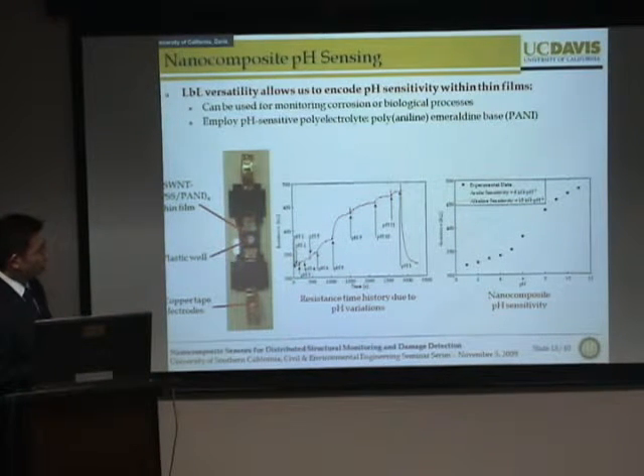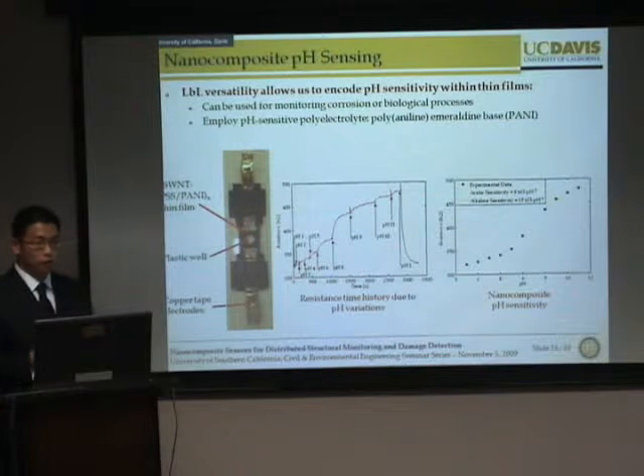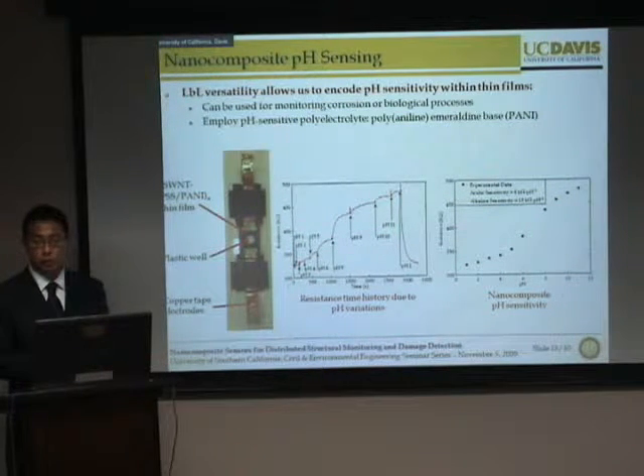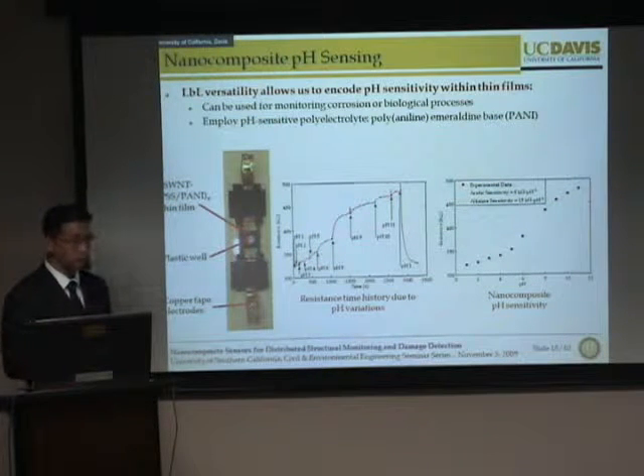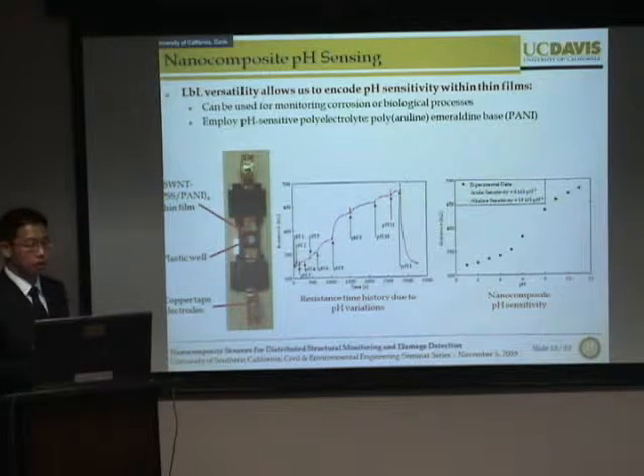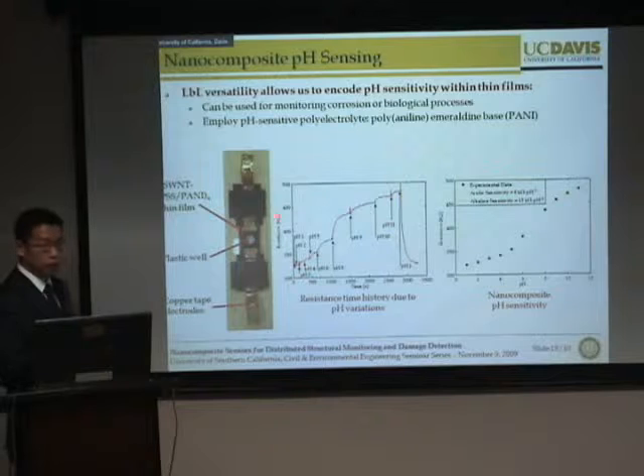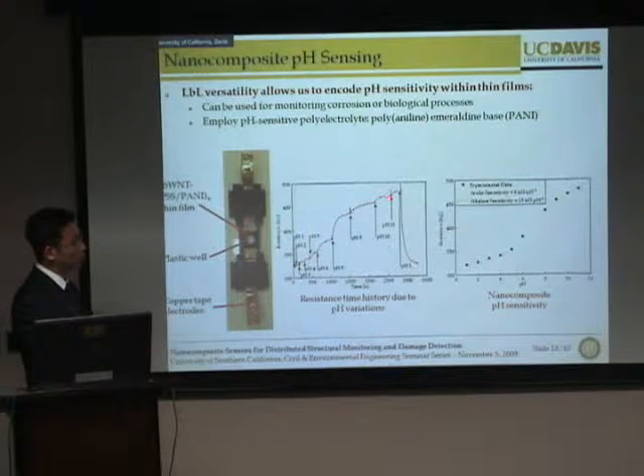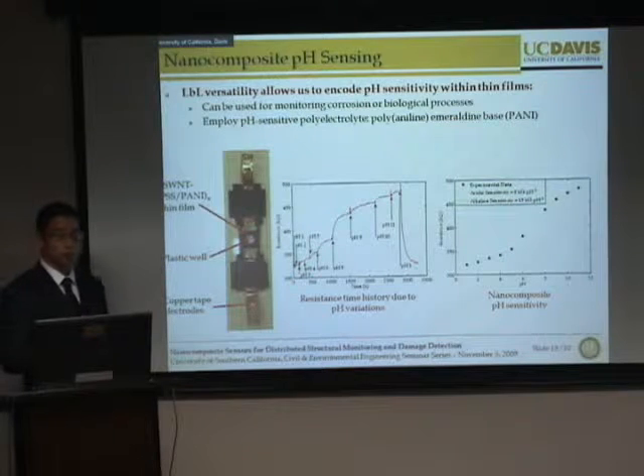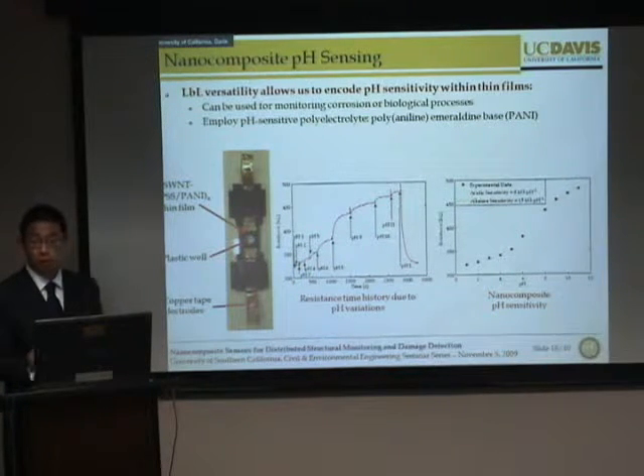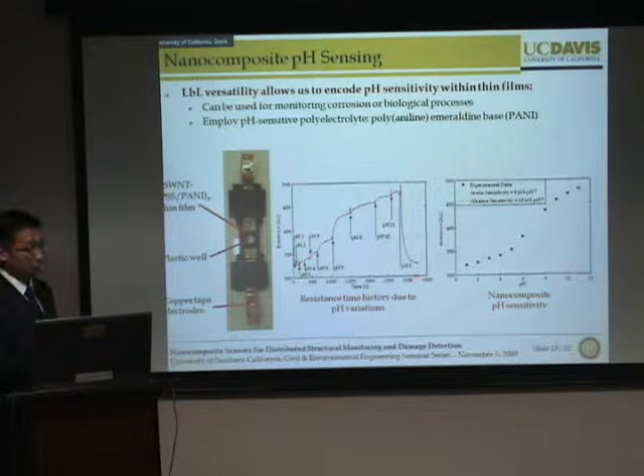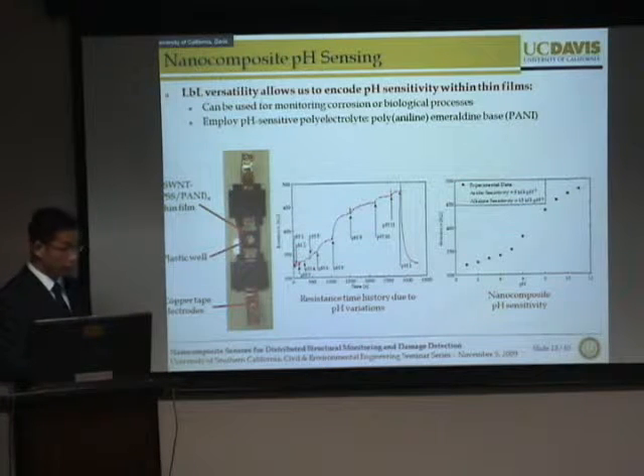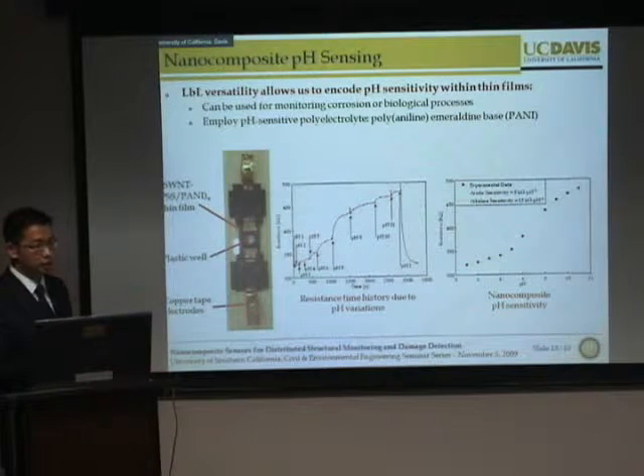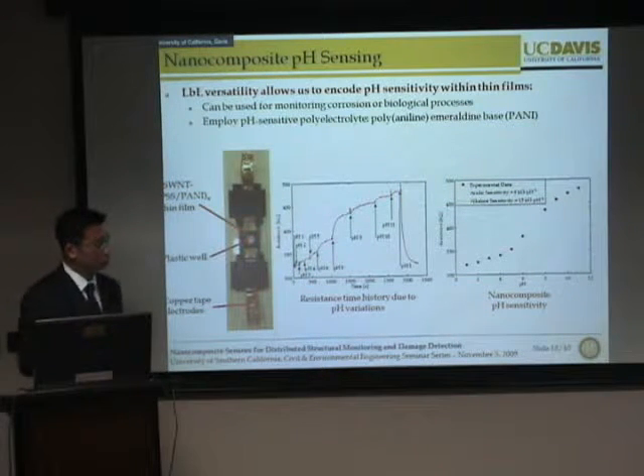So to validate the performance of this material, again, we can cut up a small specimen of this thin film. We then mounted a plastic well onto the surface of the thin film, which will allow us to pipette in different pH buffer solutions to expose these buffer solutions to the surface of the film. And then again, we'll measure the resistance as a function of time using our Agilent multimeter. Shown here is the time history record that we obtained for the thin film as we pipetted in pH buffer solutions from pH 1 to pH 11. And what you can observe is that the resistance of the material actually increases in tandem with increasingly applied pH solutions. And furthermore, upon the addition of a pH 1 solution, the resistance drops back to its original nominal resistance. And we can see that the material behaves sort of bilinearly in the acidic as well as the alkaline domain.